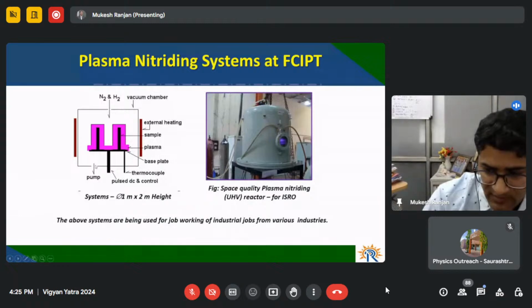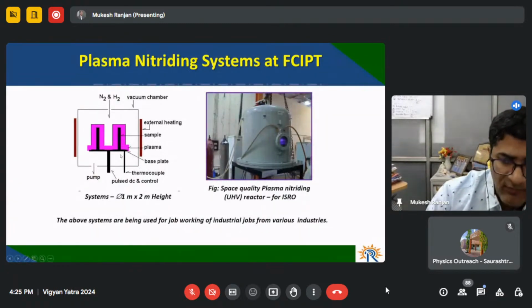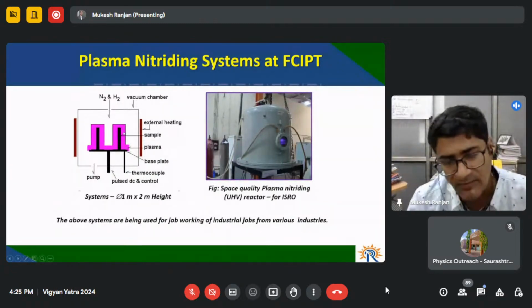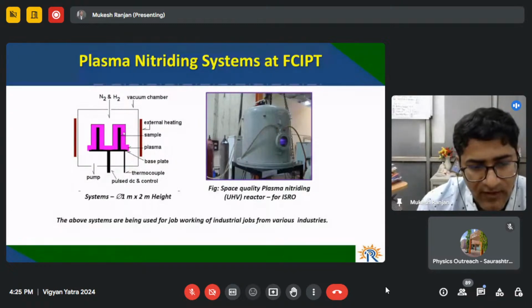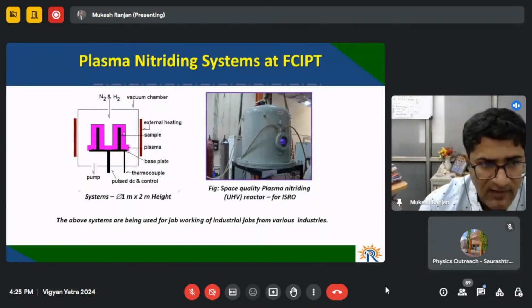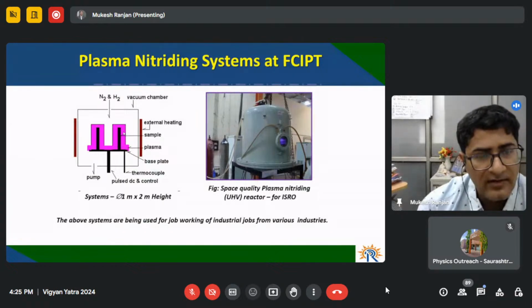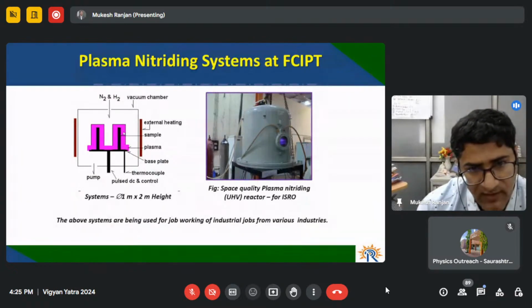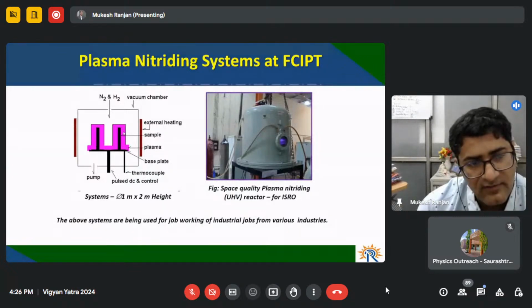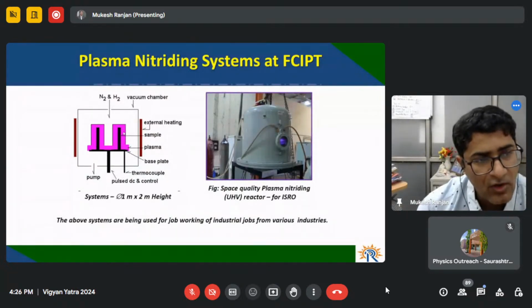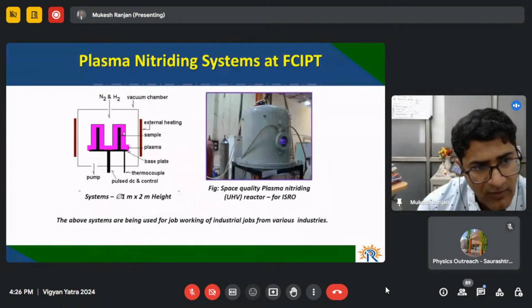Because SS is conducting, once you connect it to the negative power supply, it will attract the nitrogen ions. These nitrogen ions diffuse inside the layer of your steel. We know steel has a problem: if something made of steel is lying outside, it will very easily rust. After some time, you will see the color changing and becoming reddish, as iron oxide starts forming. Also, if a tool is used very frequently, industry wants the lifetime of this component to be much longer. That's the reason this plasma nitriding process is very effective.